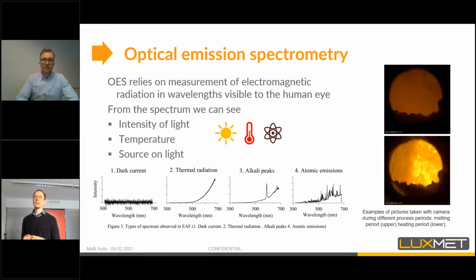For example, if we are seeing just the cold scrap, we only see dark current, no light, because the scrap is shrouding the sides. And when the scrap starts to melt, we will start to see an increased amount of thermal radiation, because the arc radiation will start to heat the surfaces. And also, sometimes we see alkali peaks, which are related to the burning material in the furnace. We will go back to this a bit later. And also, if we see the arc light itself, we also see a lot of atomic emissions coming from the hot plasma.